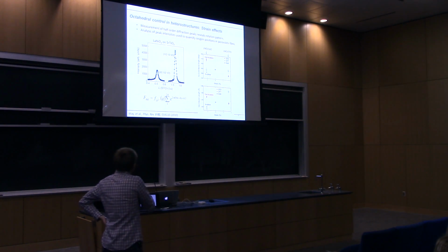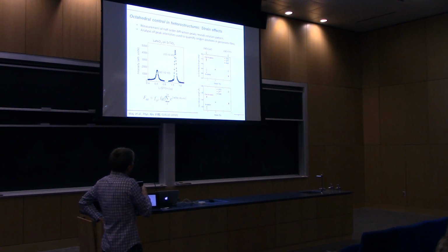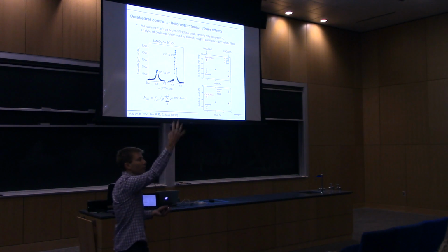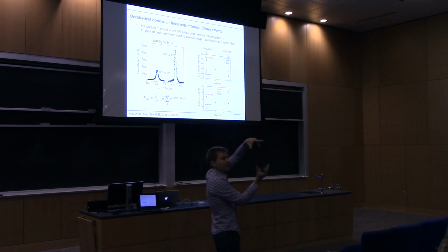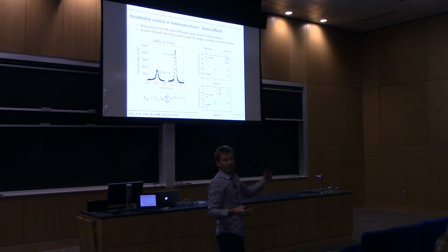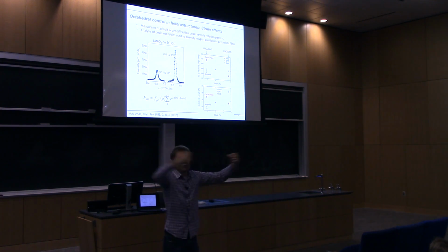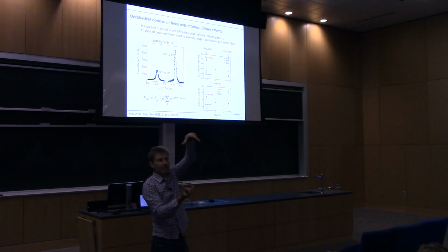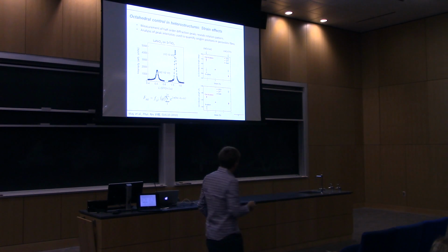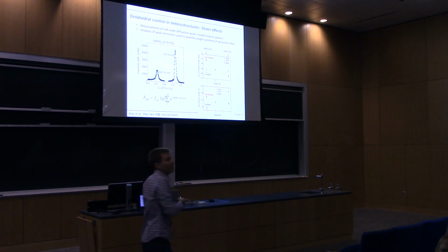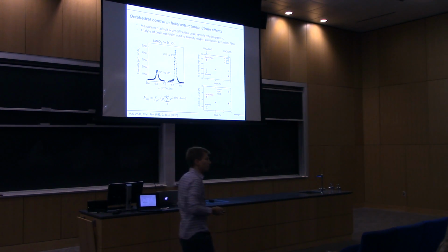And so we've done this, for instance, in lanthanum nickelate, and we've looked at how, when you grow the material under compressive or tensile strain, these octahedral rotations accommodate that strain. And it does exactly what you would think. If you stretch it, it unrotates about this axis and has to rotate more about the other axis. But it's nice to have a technique and to actually experimentally demonstrate what happens under strain.